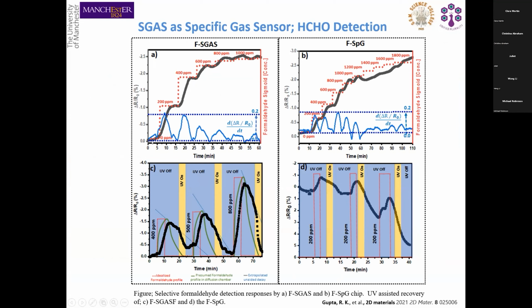The concentration of formaldehyde might be very high, because around 1 ppm, 1 to 10 ppm is very, very dangerous if that's available in your environment. But these were the early tests where we just wanted to see the efficacy of the device, whether it detects formaldehyde among different availability of other gases. That will be shown in the control experiments.